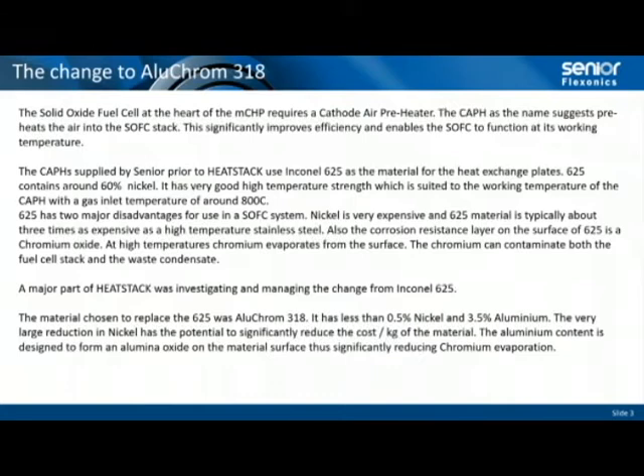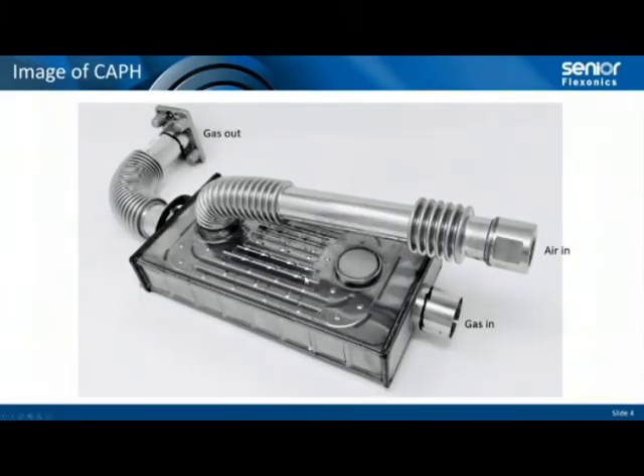So working with Vaillant at the time, at the start of HEATSTACK, it was decided that we needed to change the material away from 625. We did initially try a different AluChrom with a higher percentage of aluminium, but that was almost impossible to work with. So we went for AluChrom 318, which has 3.5% aluminium, which is just above the minimum aluminium content to ensure that the surface regenerates. Very low nickel content. So with this large reduction in nickel content, we have the potential for significant cost reduction, and because we have an alumina surface on the material, not a chromium oxide, the chromium evaporation is much reduced, and Kun will talk about this activity that the University of Birmingham did.